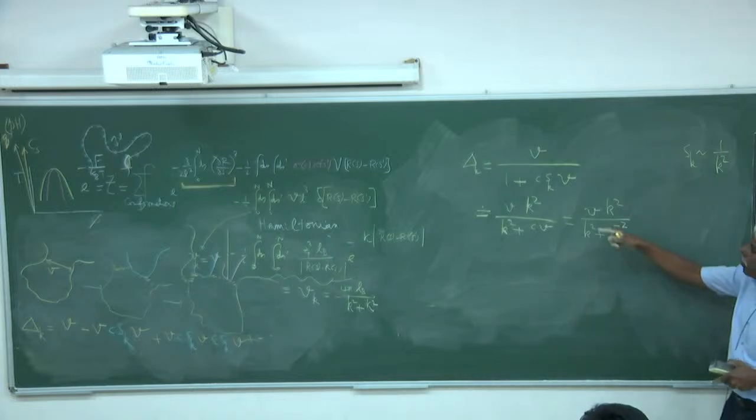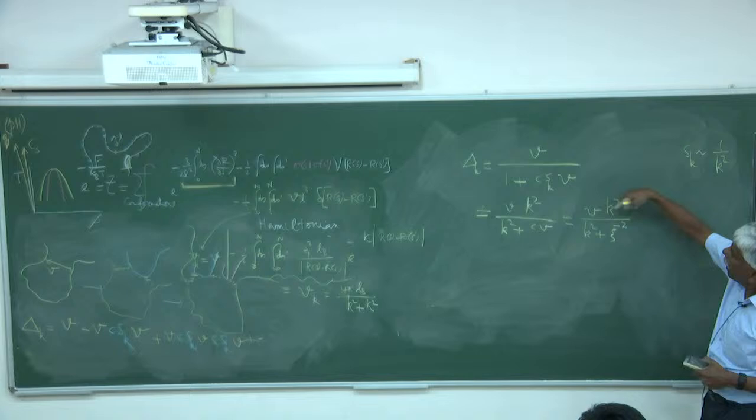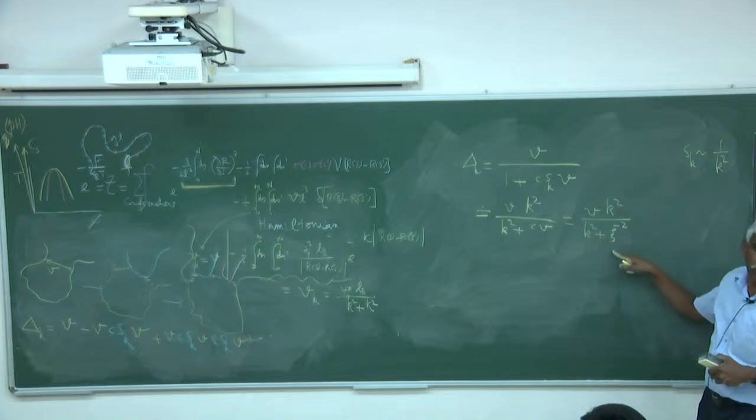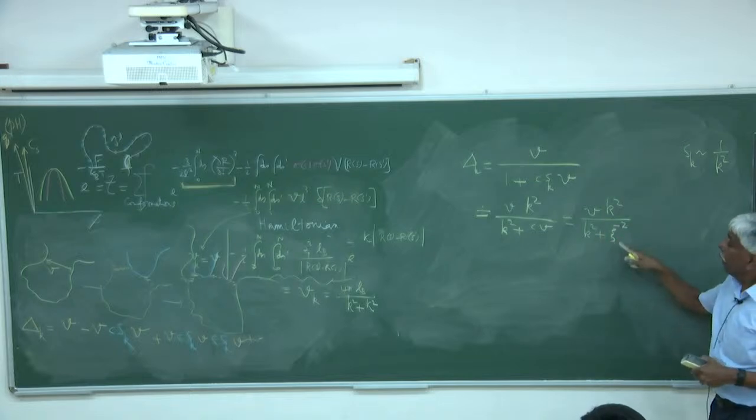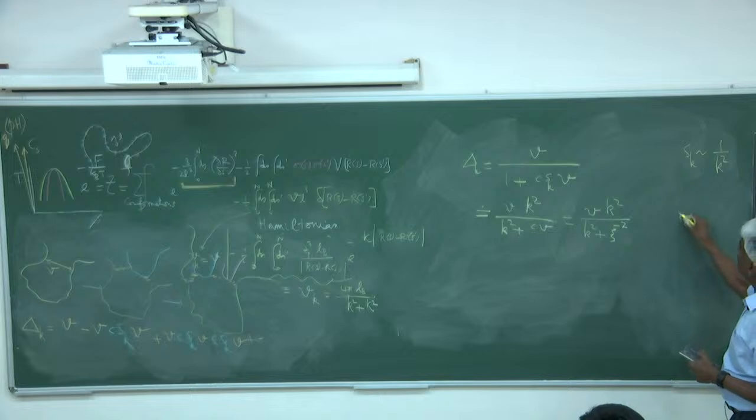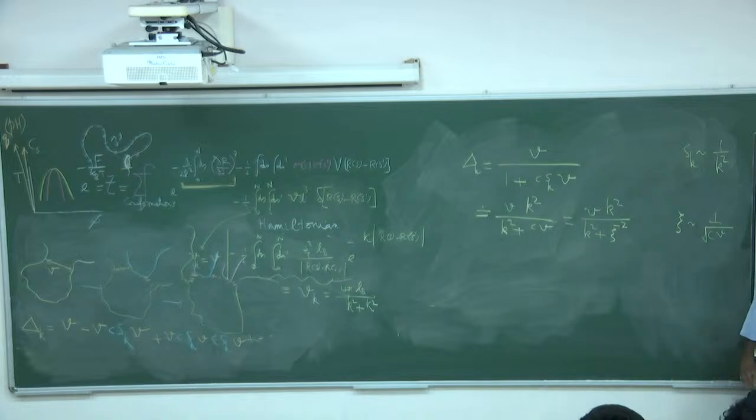Okay. That means the excluded volume interaction that you had is screened. The meaning of that is, originally I had this interaction. Because of the interpenetration of the other chains, the net effect is to screen this. Therefore, when you go to higher and higher concentration, although it's a good solvent with a swollen chain, it becomes like a Gaussian chain, because the excluded volume interactions get screened. It's called topological screening. I call it topological screening. Okay, that's for the neutral case.